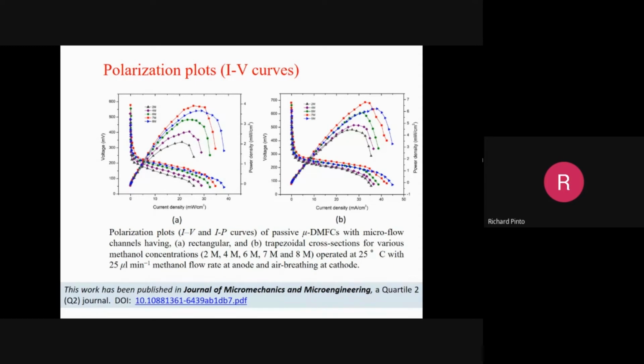It drops very fast when you draw the current, then remains flat for a long time, up to about 25 milliamps per square centimeter of current density. This should be milliamps, actually, and not milliwatts, so that is a mistake. So you have this kind of plot for voltage with current density, and on the right side is the power density, in milliwatts per square centimeter.